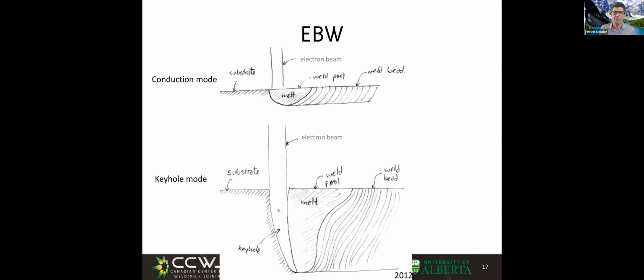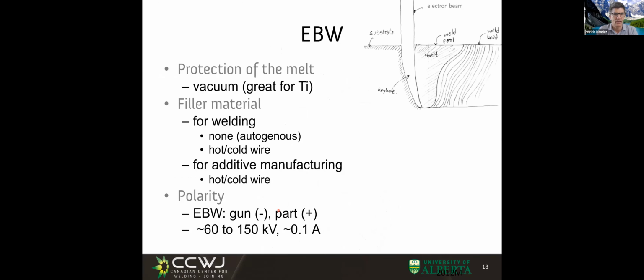Now, there are very important differences between laser and electron beams. Number one, in electron beams, you tend to operate them under vacuum, either high vacuum or low vacuum. The Soviets tried no-vacuum processes too. But in general, the electrons don't fly very far if there is a gas between the gun and the plate. So you tend to do it in a vacuum, which is a fantastic thing for materials like titanium that are so highly reactive with contaminants. So now you have the best of both worlds. You needed a vacuum for your welding system, and you wanted the vacuum to protect your material. This is the way you weld jet fighters.